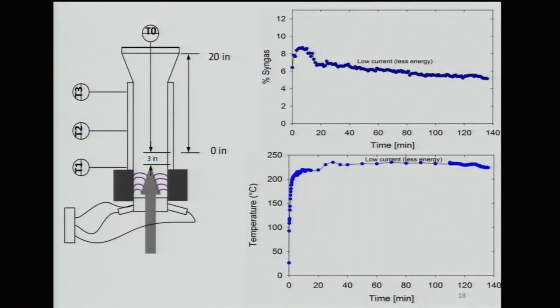So basically, all the temperature that you can see here is coming from the movements of the molecules, from the reaction itself. So as you can see, we have this pretty steep slope increasing temperature during the first minutes of the reaction. Then, at around minute 30, it reaches a plateau, the steady state. So then we perform the other experiment.